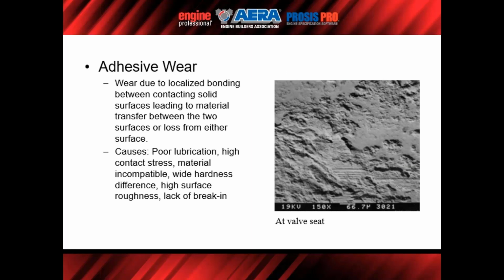All right. So adhesive wear, so the micro welding, again, if you take a look at, do I have the right seat material for that valve material? So now I'm battling micro welding. This is just kind of a blown up view. You can tell you have some nice flat surface area, and then you have areas that are pulled out, due to localized bonding between contacting solid surfaces. Again, just reiterating, poor lubrication, high stress, wide hardness differential between the valve and the seat, surface roughness, which increases friction, and could be heavy duty cycle without break-in.